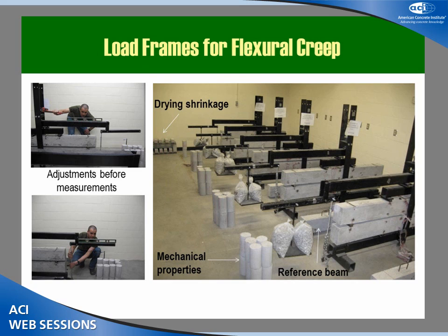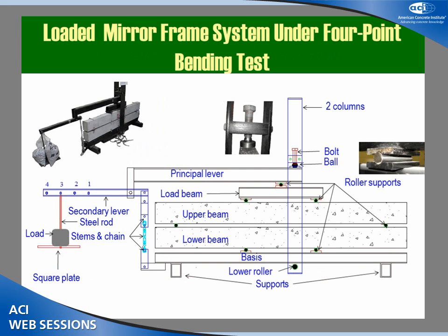So we are putting what we call mirror type of beams in a frame with a cantilever where there's a load suspended, applying a certain load on the beams. So there's a central load over here, causing the beams to be under sustained load for a very long period of time. And we are looking at the deformation of the concrete, of the steel, the strains, under sustained load for over a year.